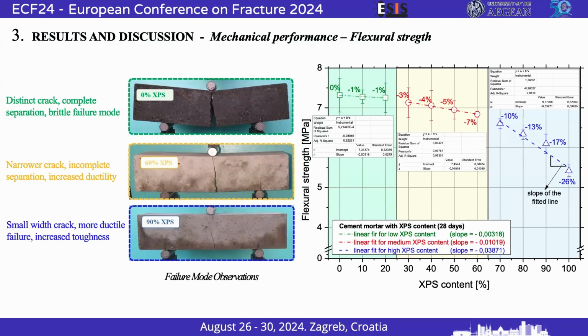It is interesting that while the compressive strength decreases 46%, for the flexural strength the reduction is much lower, 26%. And we have also seen a different observation in the failure mode. If we look at how the reference sample has cracked, we have a steep crack, and it is a brittle failure mode. While when we increase the XPS content, the material has a more ductile failure and the fracture of the material increases.